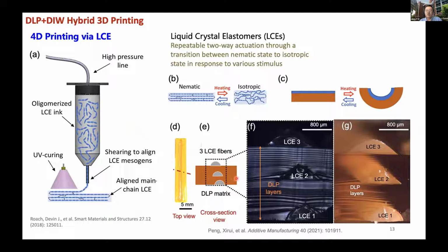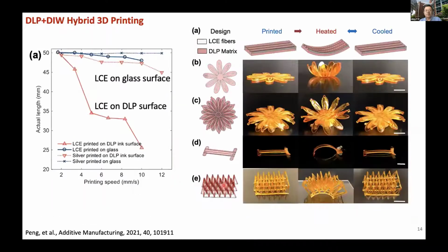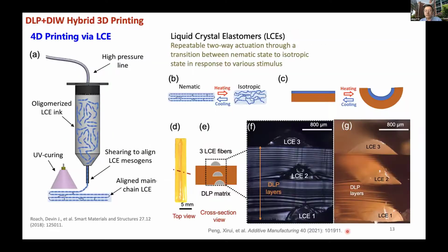So you can see here, in this case, we can print the structure. We can add multiple LCE fibers. You can see here, this one LCE, the other LCE, this is the third LCE. The LCE we used here also has acrylate. The mesogen itself is acrylate based, so it also shows very good compatibility with our DLP ink. So we have a relatively good interface.